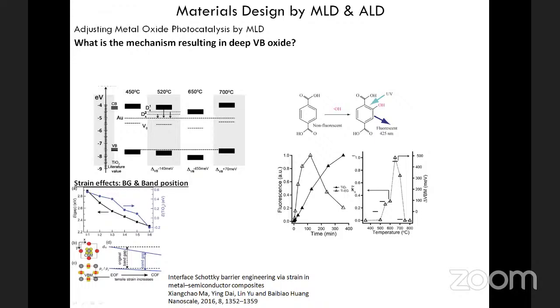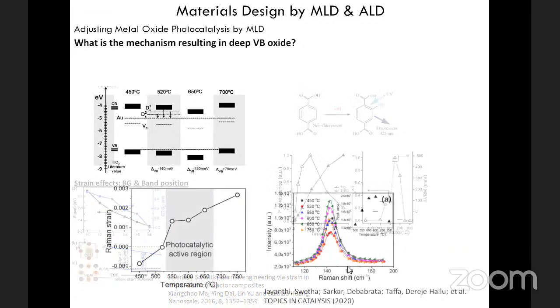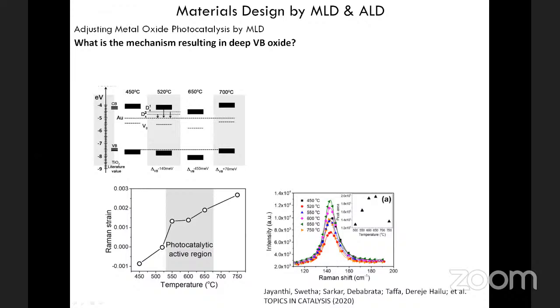And this was for a while a bit difficult to pinpoint, until at some point it became quite known that strain effects in oxide affect band gap and band position. And this is a reference to some of the papers that showed this very nicely, where inherent strain in the oxide can shift the band positions and also modulate band gap. So we decided, and Debu contributed significantly to this work, we decided to look into Raman data that we had, and Raman position of certain peaks of the oxide can assist in quantifying inherent strain in the oxide.